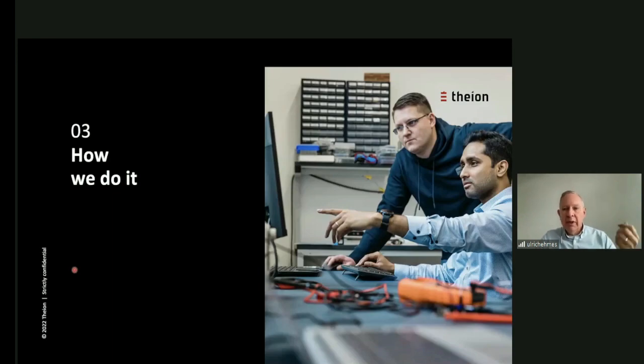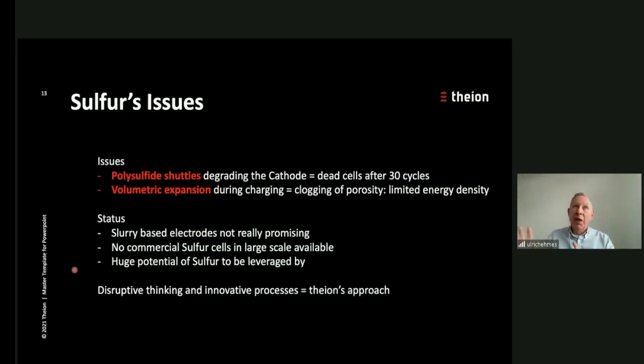So how do we do it? Now let's talk a bit about the issues of sulfur. There are two issues with sulfur. The first is that when we charge and discharge, polysulfide shuttles build up. And these shuttles are corroding the cathode, and then normally after 30 cycles, the cell is dead.